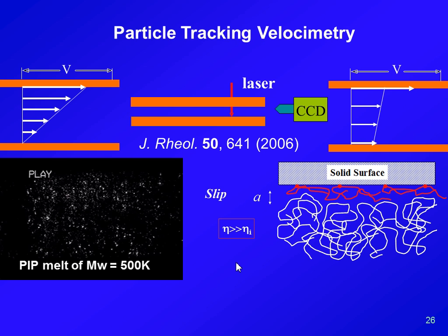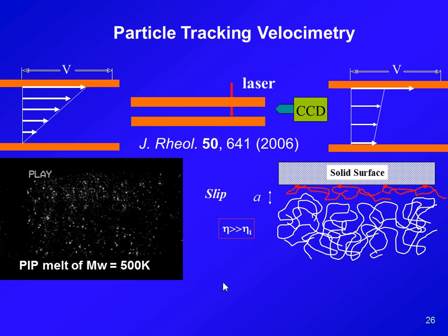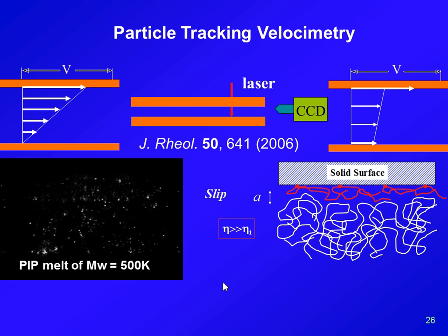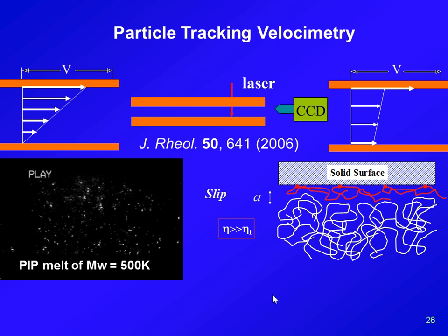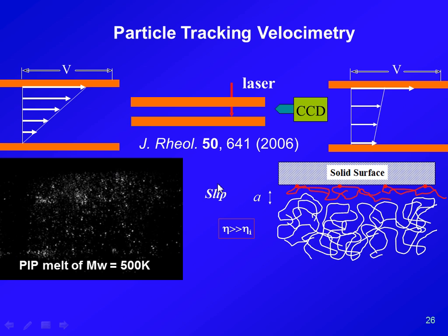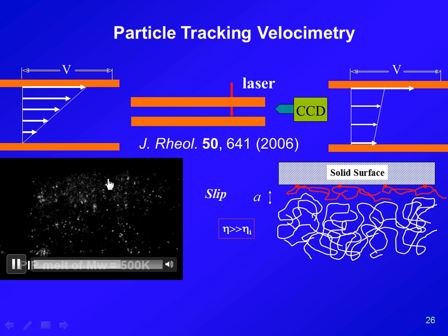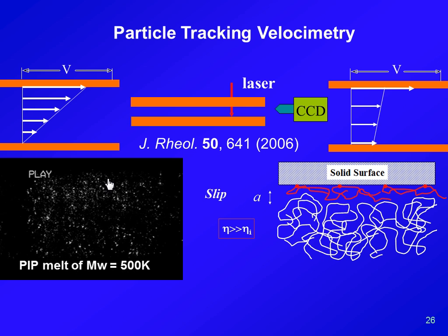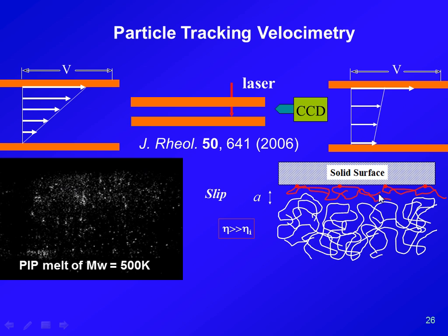And I return to reality again, that you cannot go processing, you cannot go to a rheology lab without worrying about the interface between the polymer and your sample, and the wall. And this is another particle tracking movie. I don't know if you can make sense out of that movie. It's going to repeat again. You shear, start up right away. You see, it's all nice. And that's the point where the polymer is still in good interaction with the surface. So that allows this shear to continue homogeneously. And the movie subsequently shows, upon breaking, watch, it retracts because there's nothing to grab the sample anymore from the surface. Ultimately, you see, that's ultimately steady state. You have this constant slip, as I depicted.